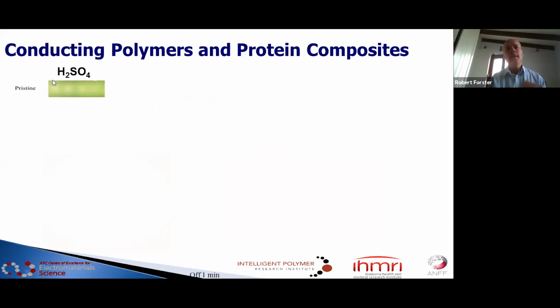What Shunyan has done is to take fluorine doped tin oxide and electrochemically deposit a conducting polymer, for example PANI, onto that surface, and then look at what happens when you induce a potential within that electrode.